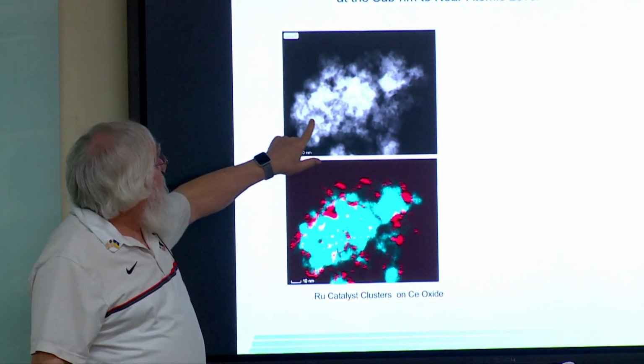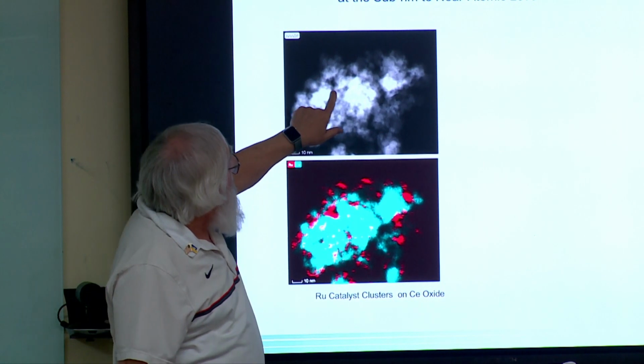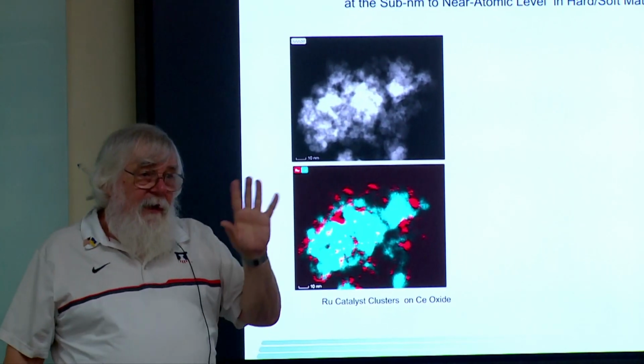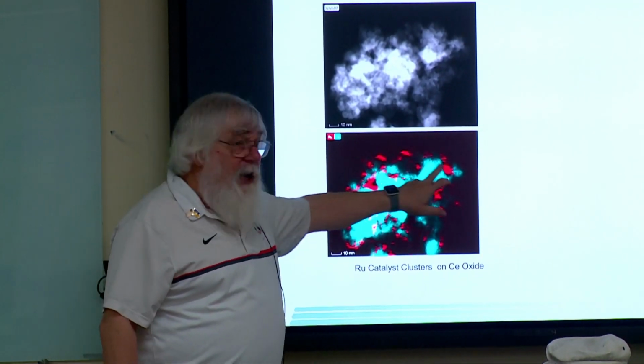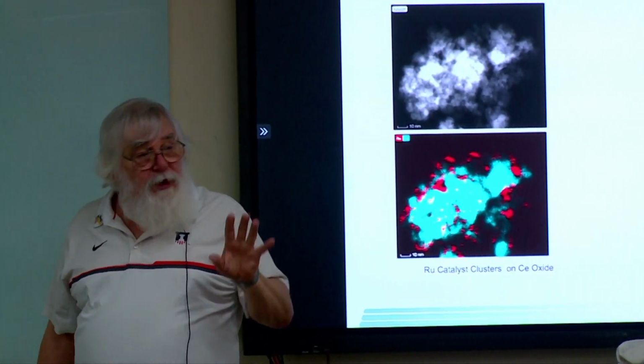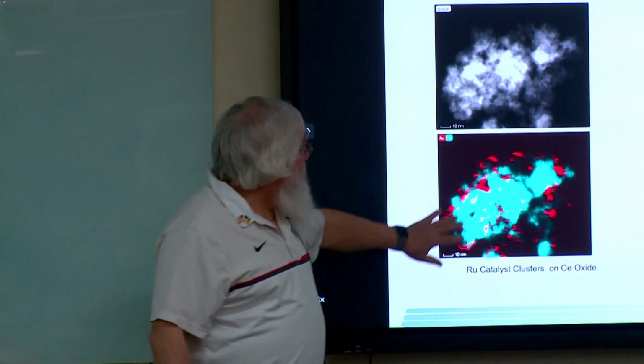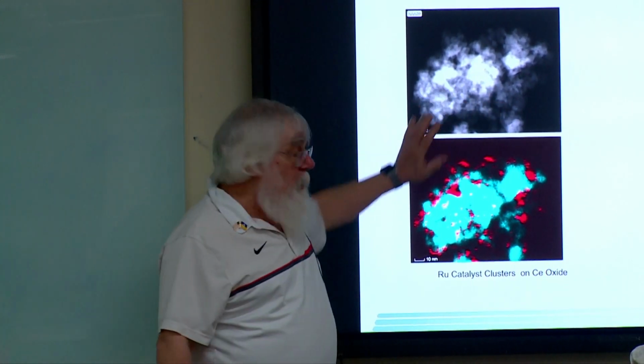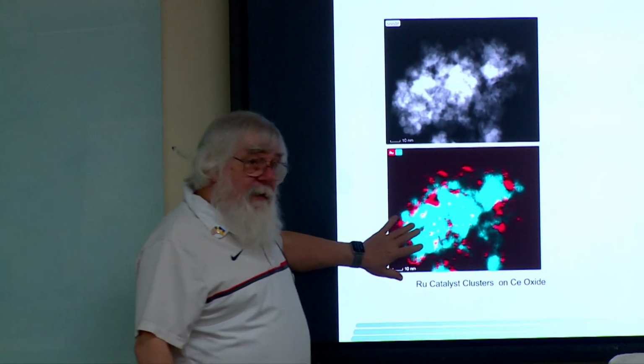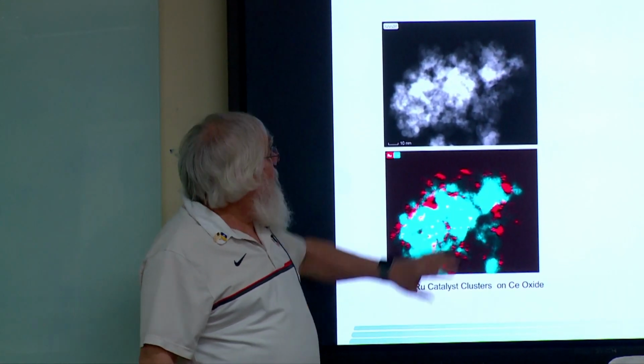The catalyst, if you can see them, they're small, very little tiny white dots there. That happens to be, and now you see them in red, the ruthenium, which is the catalyst. So the cerium oxide in blue is the support. The ruthenium in red is the catalyst, and that's the thing we're interested in. So how do we know where it's there? We have to use a subsidiary or other analytical processes to see them.